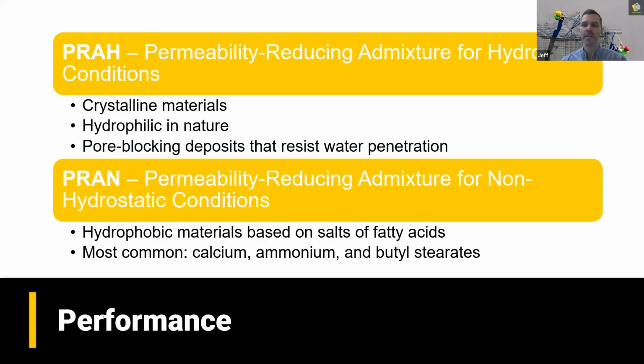Now, Chapter 15 describes the materials, the role and function and capabilities of this class of products, and it broadly breaks them down into 2 categories. Those are permeability reducing admixtures for hydrostatic conditions. Now, these would employ some sort of physical pore blocking mechanism, such as crystalline growth, that is able to physically block the pores and capillaries against water penetration and maintain that protection over the long term, even when exposed to high hydrostatic pressure, like you might get in a water tank or in a below grade structure.